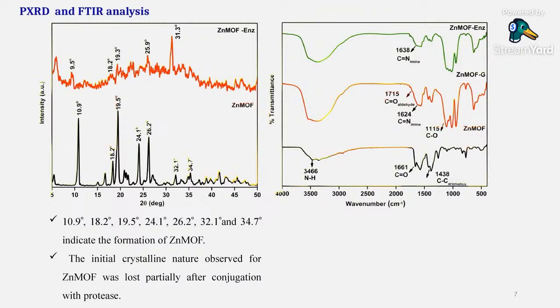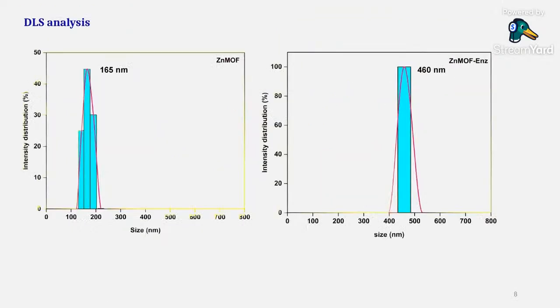Once we did this, we did the FTIR also, IR spectroscopy, where you will see the changes happening in the functional groups. In the zinc MOF here, you can see the NH group from the amino terephthalic acid. After conjugation, it becomes more broadened, and you can see all the CN binding and the CO of the glutaraldehyde, zinc glutaraldehyde, which is absent once the enzyme is coating over the surface.